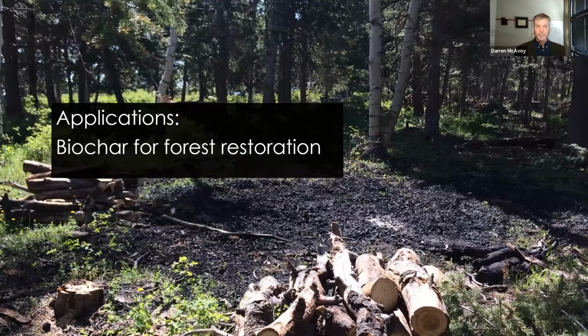This is a little small box kiln operation in Soldier Summit, and in very heavy fuels we were operating in June or July, almost the heat of summer, but operated quite safely. And we just use grain scoops at this scale to spread the char out onto the ground as best as we can, especially in landings, heavily impacted areas. And we find over time it'll work itself into the ground. Coming into the job in the morning, sometimes you'll find deer eating the char, rolling in it, really interacting with it in surprising ways.